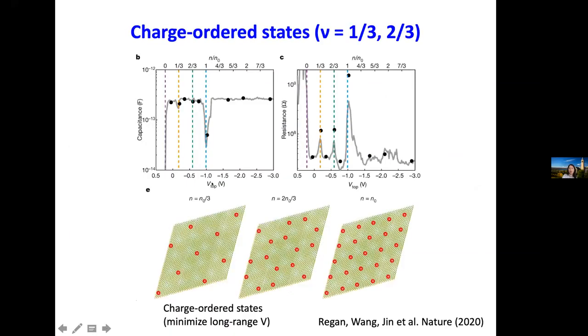And Feng Wang's group at Berkeley invented this pretty clever scheme to measure the charging dynamics into the Moire superlattice by optically looking at the connected piece of monolayer, to see how the exciton changes when you dope the superlattice. And they were able to see the 1/3 and 2/3 peaks in their resistance channel, and they assigned this to a generalized Wigner crystal state of holes in the TMD Moire superlattice.